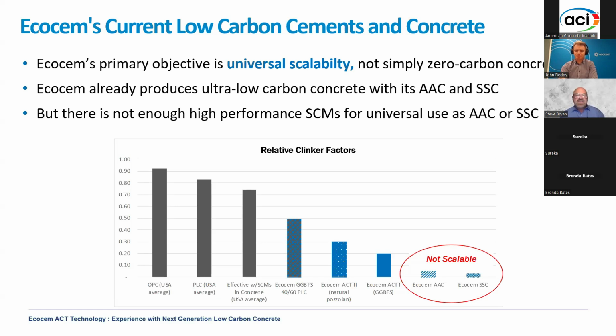If you look at the chart below, you'll see that those two products are on the far right. You can get a somewhat relative perspective of their carbon content by the scale here that's based on clinker. Then on the far left, you see conventional OPC, then PLC, which is introduced in the USA this year. And then you look at typical mixed design with SCMs along with PLC. And in the middle, you have 40% GGBFS with PLC. So you can see then that Act 2 with natural pozzolans and Act 1 with slag offer a very significant reduction in embodied carbon, even relative to a go-to mixed design of 50-50 OPC and slag, or 40% GGBFS with 60% PLC.